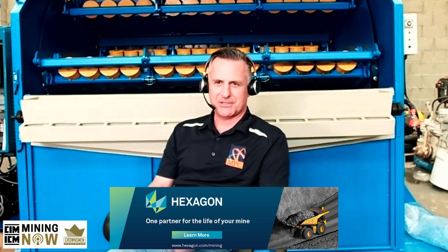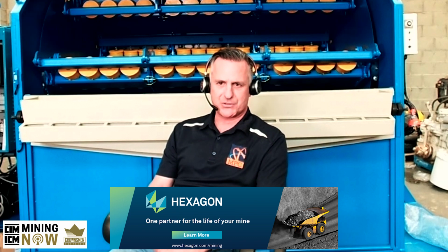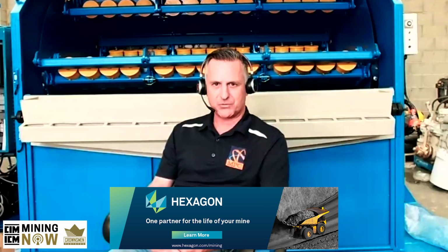So if you look behind me, you can see the PEL open, and the yellow pots you see are cast iron pots with grinding media in there, which is cast iron balls. You'll put, say, 2 millimeters upwards. Some customers use up to 10 millimeter feed size, so quite coarse. It gets loaded straight into the pot, and you put the lid on with the cyanide tablet. 2 assay tabs go in there, and it rotates around, which I think there was a bit of a video of in the last interview, which you can look at. That basically grinds and leaches at the same time, using the assay tab to extract the gold and the LeachWELL component to accelerate that process.